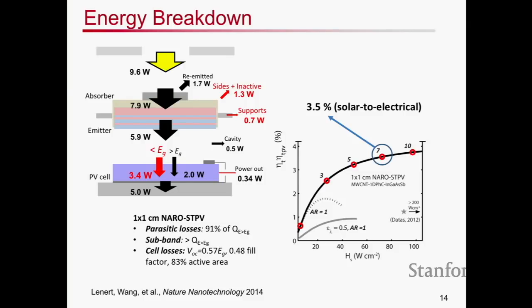And certainly because we were dealing with a relatively small size scale device, on the order of about 1 by 1 centimeter, there are still a lot of parasitic losses from the supports and the sides and inactive area, for example. And there's only a certain amount of energy that's hitting the PV cell. We said, I think we could do better if we think about the fact that the amount of energy that's above the band gap is only a portion of what is then also getting lost below the band gap, right?